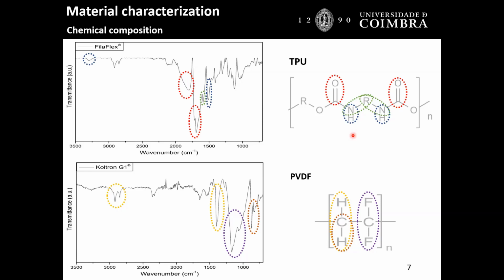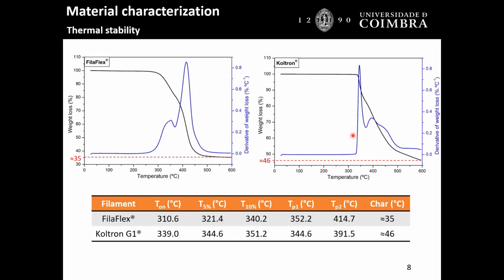So then we made a thermal stability analysis in order to have an idea of the temperatures where we should process the polymers during the printing process. And what we saw is that in fact we have stable polymers around 310, 340 degrees Celsius. Of course, PVDF-based filaments are more stable at high temperatures. Nevertheless, we are not going to go to printing at this temperature.